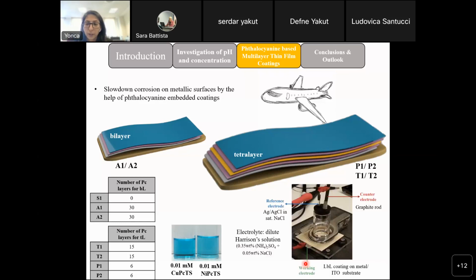And all of the electrochemical measurements are done in this unit cell. So what we have is a reference electrode, silver chloride, and a counter electrode, which is a graphite rod. And the working electrode is the sample that is coated. In order to simulate the atmospheric conditions for aerospace applications, dilute Harrison solution is used. This is one of the suggested electrolyte compositions in the literature.